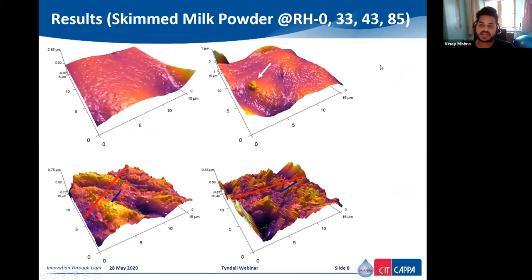So this is skimmed milk powder. I scanned 9 different samples, from 0, 11 to 85. Right now, I'm showing 4 different results where the major changes in the microstructure on the surface of the sample are seen. So right now, this is a relative humidity of skim milk at 0, 33, 43, and 85. You can see clearly that at lower moisture content, where there is less moisture absorption on the surface, skim milk powder appeared smooth as compared to the region where there is higher moisture absorption on the surface.